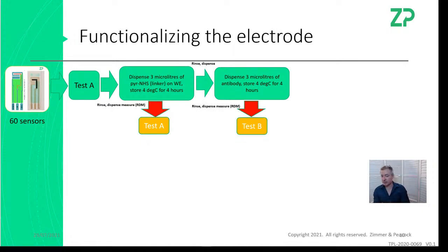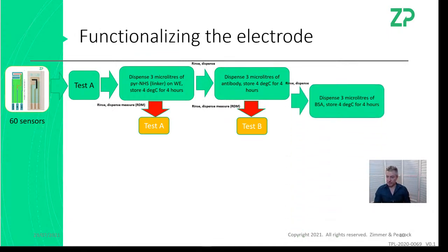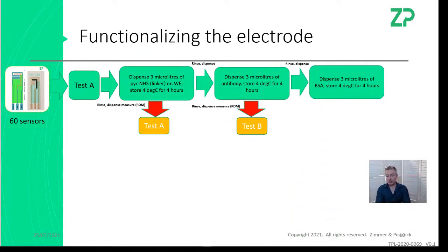So every time we're testing them by cyclic voltammetry, we're making sure that we're altering the surface, and we should see a change in the cyclic voltammetry. So we start off with something like 60 electrodes. We test them by cyclic voltammetry, make sure they're good. We put the coupling agent on. We test a few of them to make sure that the coupling agent went on the surface. We take them through, and then we put the antibody on them. We test them again, and then we put the blocking agent on, the BSA. The BSA is obviously the final blocking agent to stop non-specific binding, and then we test them again.